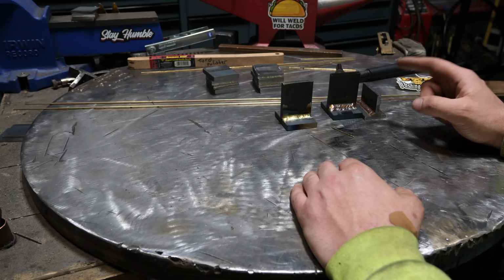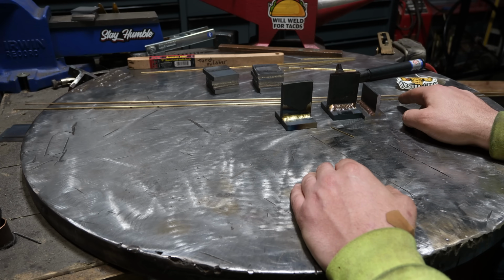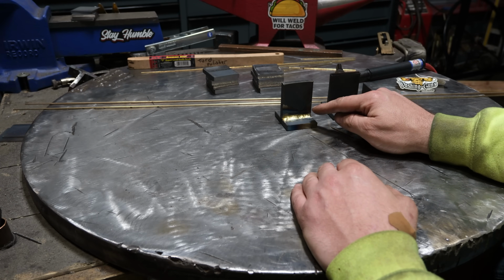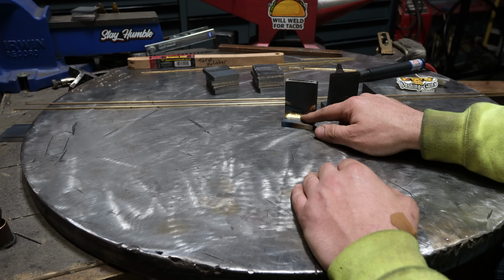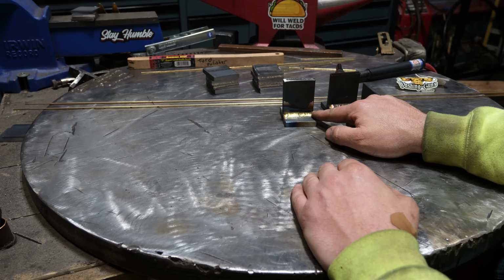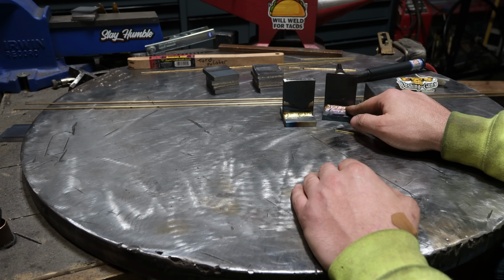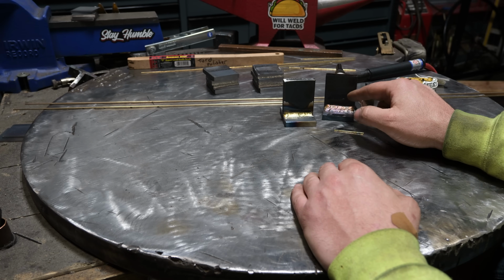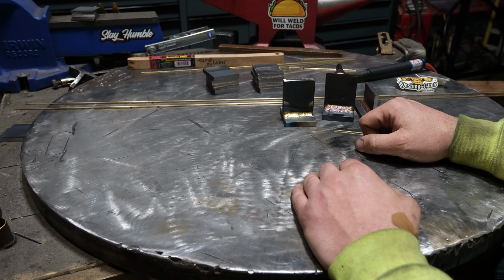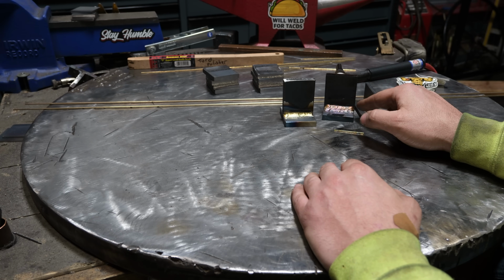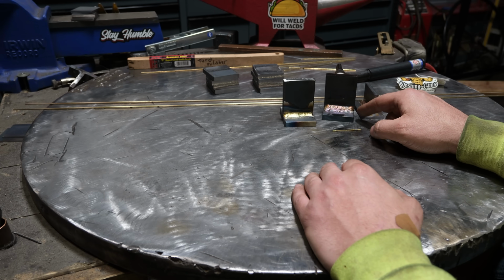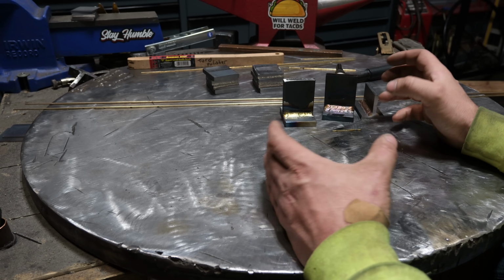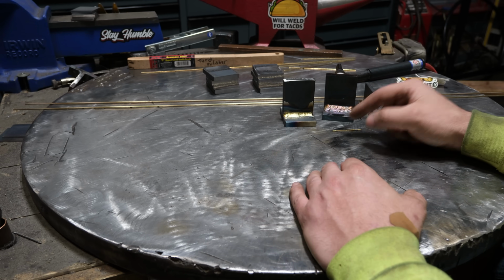Now with all that said, I'm going to start brazing these plates up with this material, and I'm going to do a set of each one with a single pass and a set with a multiple pass, because typically this stuff is far stronger with multi-pass simply because of how it functions. It's not like a fusion process, so oversizing the braze should give us the strength that we're looking for on something this thick.